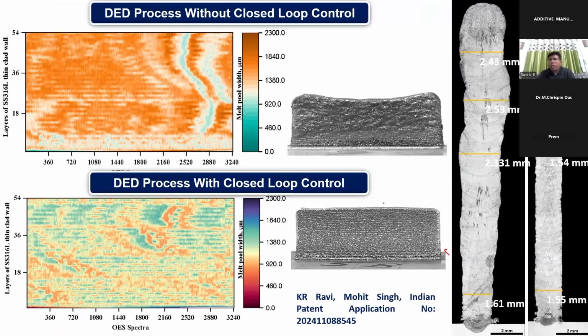So the beauty here is, as I told you, when you don't have any control, I start with 1.6 mm. When I go on top, you can see the deformation of the part is happening. Instead of forming like this, it is going this way. So there will be a deformation of parts. You see the melt pool width would be continuously changing.